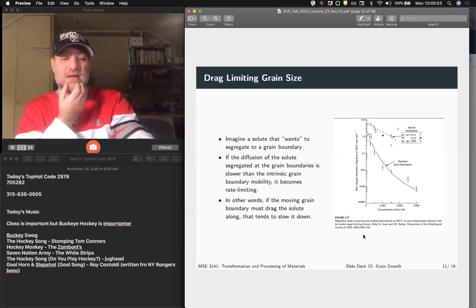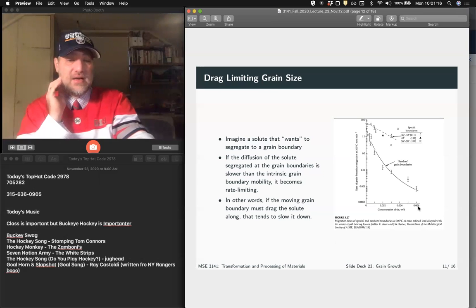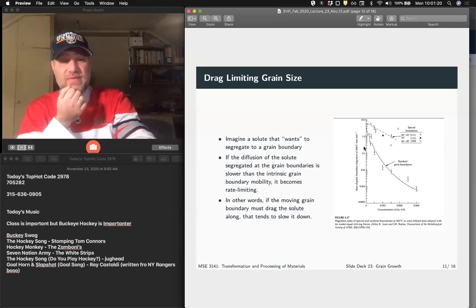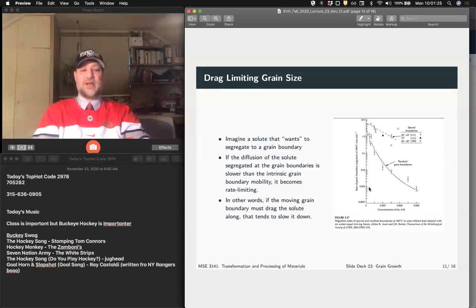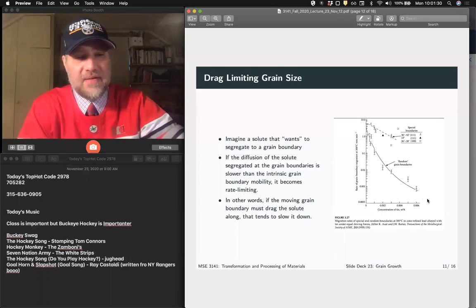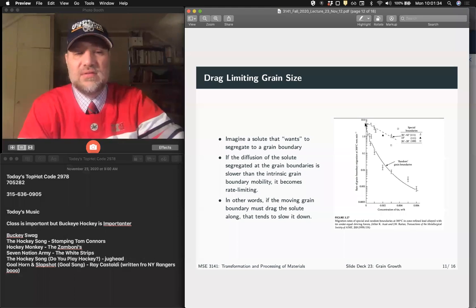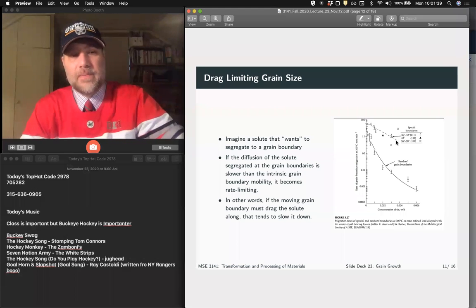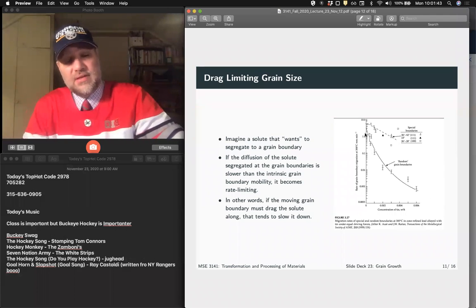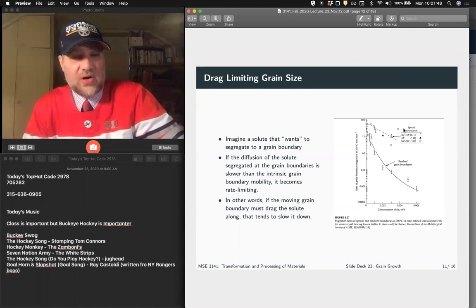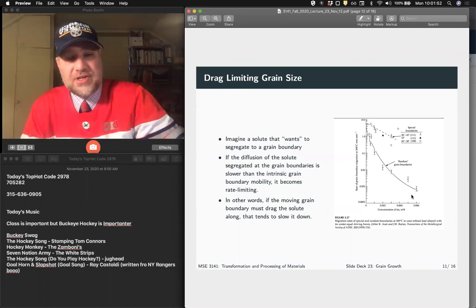Okay, and we can see this. This is a lead alloy with tin added, and this is the weight percent tin, and you can see that the grain boundary mobility drops exponentially with increasing tin content, right? Just 0.006% of tin in lead is enough to make it fall 4 orders of magnitude in grain boundary mobility. Okay, so this is broken down into random grain boundaries, and these are special, highly mobile grain boundaries. They're not as affected, but these are a very small fraction of the overall grain population, right? So in general, solutes can really slow down our grain growth.